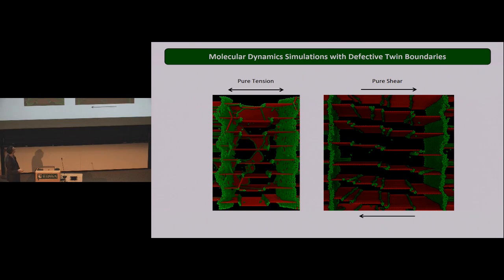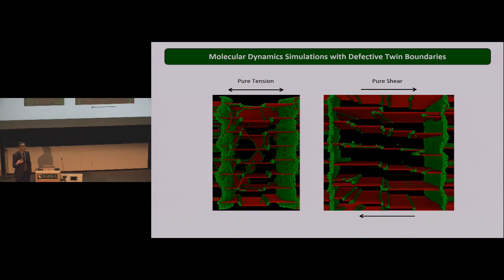the twin boundaries. And in this case, we simply shear a different model. And you'll see that these defects have their own mechanics, the small-scale mechanics they have. They will just migrate very easily. And again, this was not predicted from the assumption that we have perfect twin boundaries.